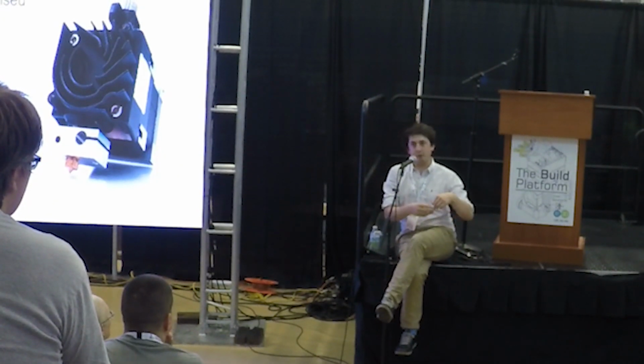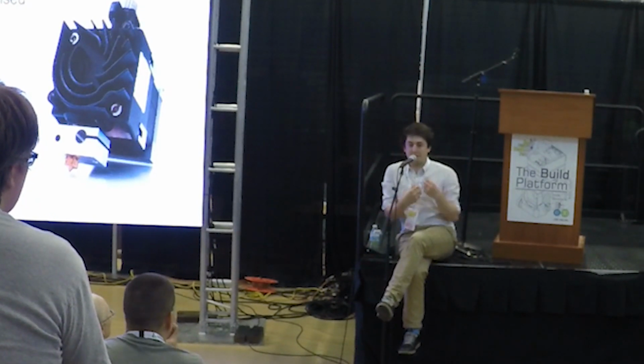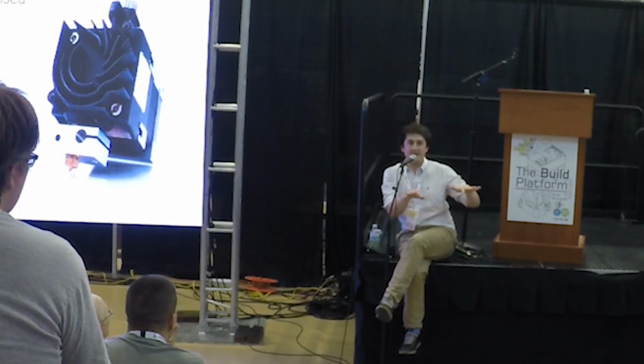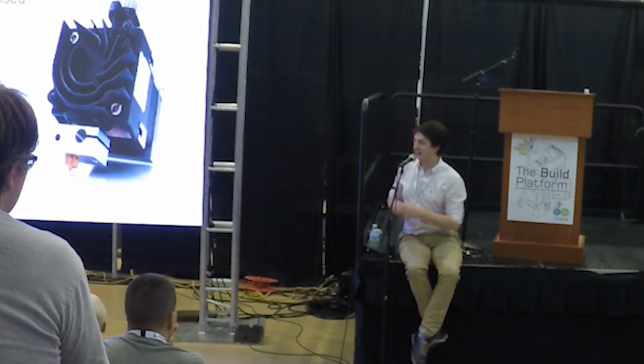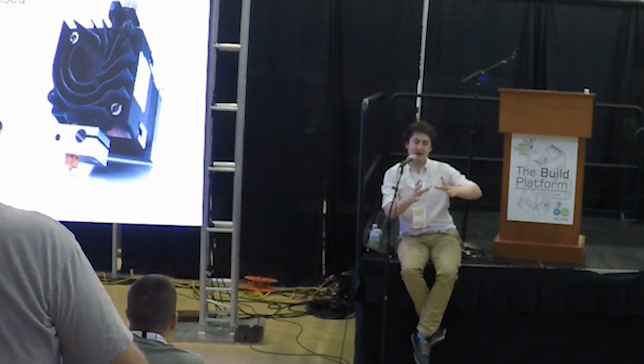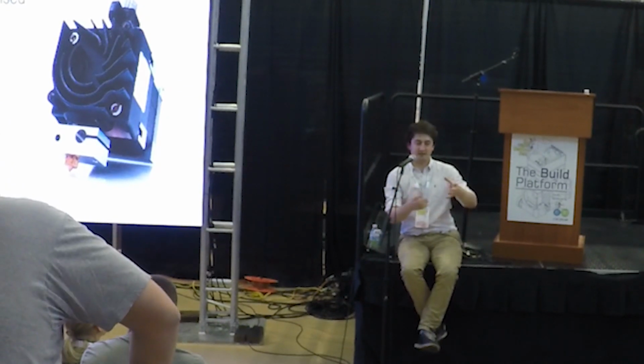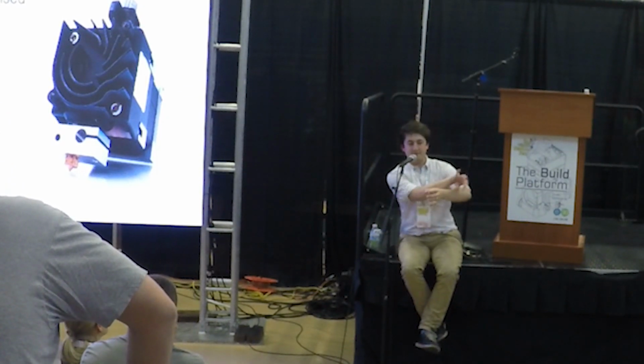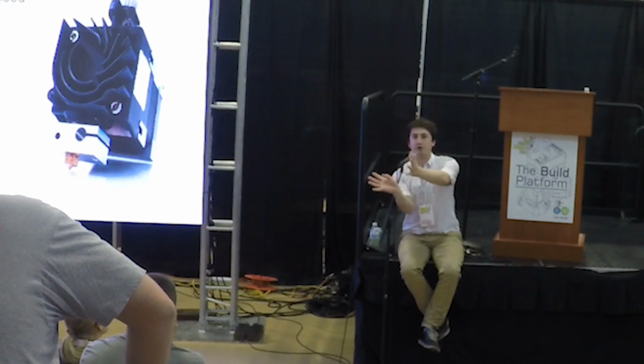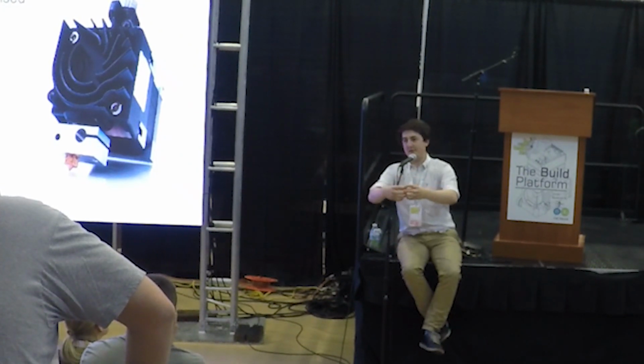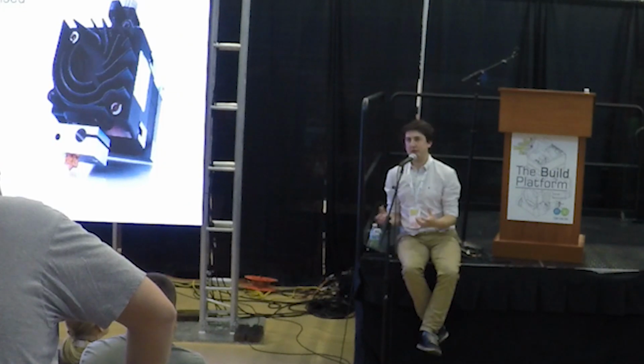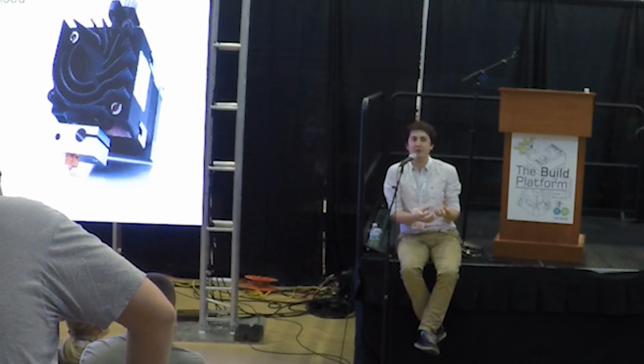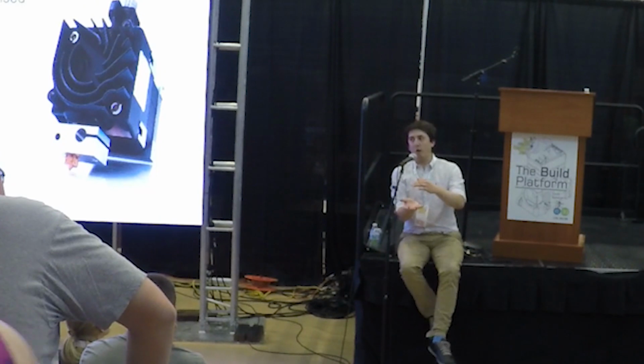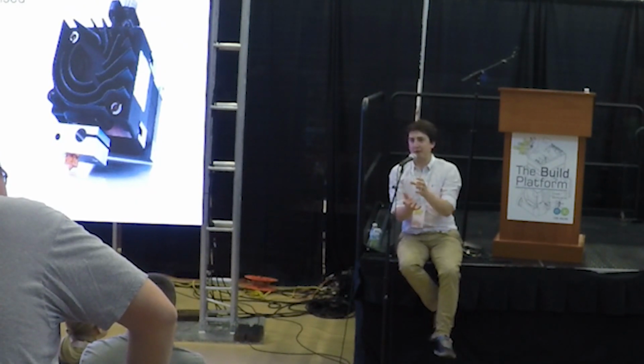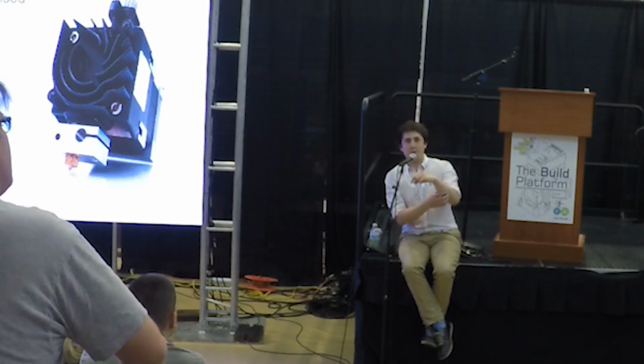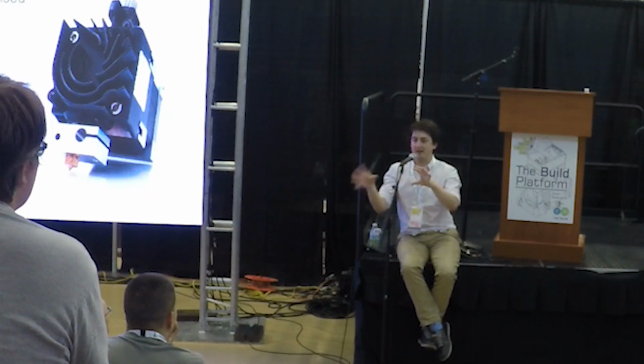We were doing it for the opposite. We wanted to try and engineer with the part cooling fan off. We didn't want any disturbances. So you should really get some pictures of this, but if you take a V6 and you run this test, you see that after the fan's pointing that way, and you can see this huge wash of air on the other side as the kind of dirty air coming out. Huge wash. It's a slight disturbance, but it's enough if you're printing like an ASA part that one side of it will warp up a little bit and crack. We've probably seen that. And the reason why it happens on one side and not the other is this kind of dirty air thing going on.